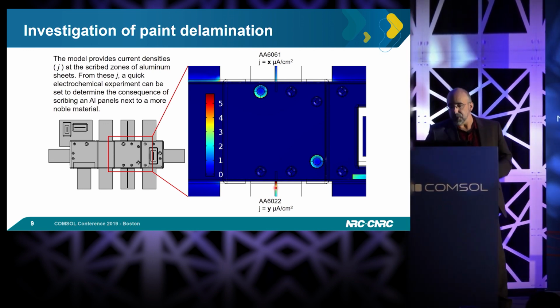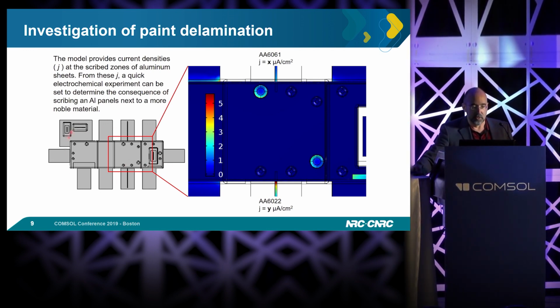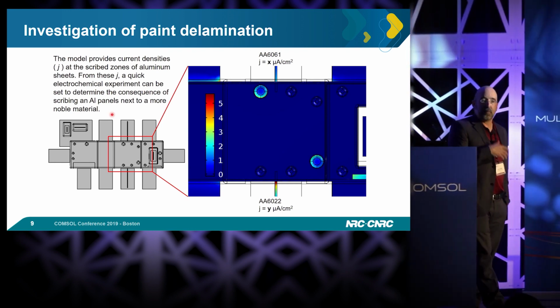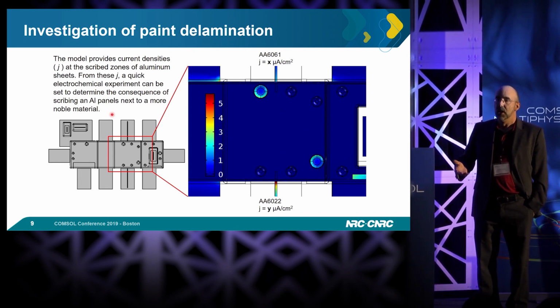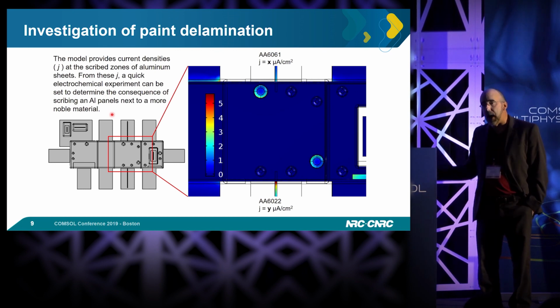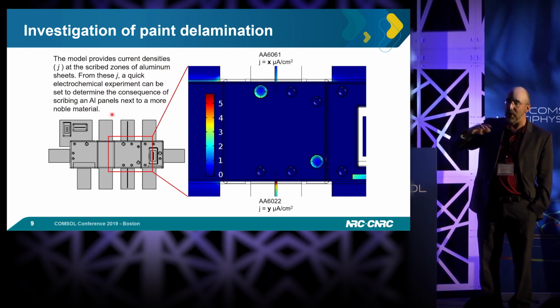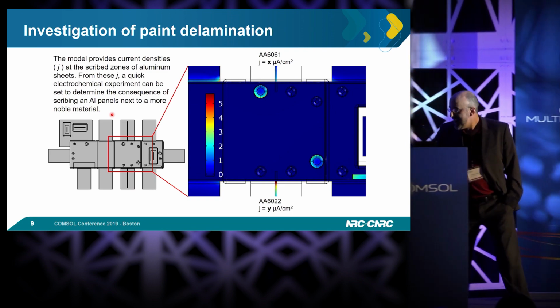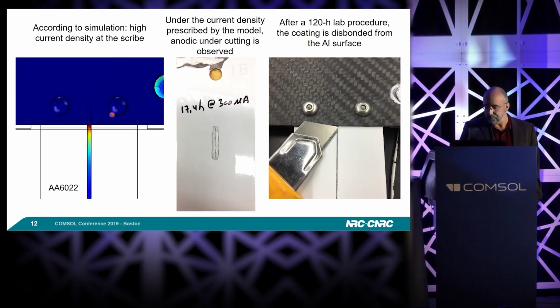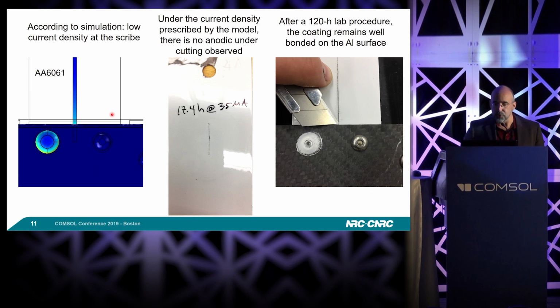So if we take this complex assembly that you see here, if we put it under a lab test, with cyclic immersion and drying and not too warm in temperature, I never go to 60 degrees C. But what is happening? This is what we've tried here. The 6061 material, very low current density, no disbonding after the polarization at the appropriate current density. After the lab exposure, we tried to peel the paint. It stayed there.